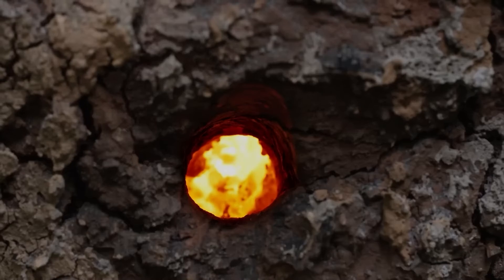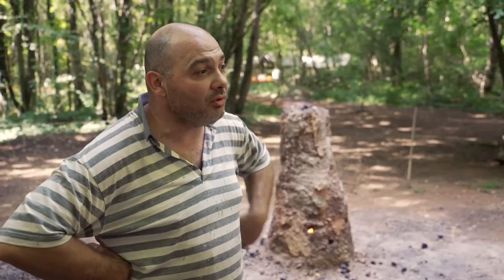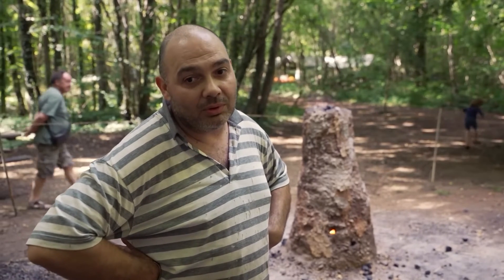If the temperature were higher than that, the metal would vanish, because it melts away at 1,400 degrees and we'd lose it all. And if the temperature is lower, the metal wouldn't be malleable. I wouldn't say we've completely mastered it because we're still experimenting. We're able to control the fire, but we're still far from being alchemists or magicians — just some guys experimenting to rediscover ancestral practices sadly lost over time.